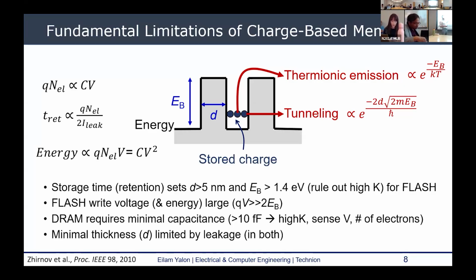And these charges can escape or leak by thermionic emission over the barrier, or tunneling through the barrier. And we know these two physical processes, so we can make some predictions and some basic analysis of the limitations. I'm not going to go into precise numbers, but just roughly speaking, for a non-volatile element like NAND flash, that sets very critical limitations on the thickness of the oxide and the materials that we can use, because we want to have fairly large barriers to get long storage time, long retention time. So these are some basic limitations for scaling.